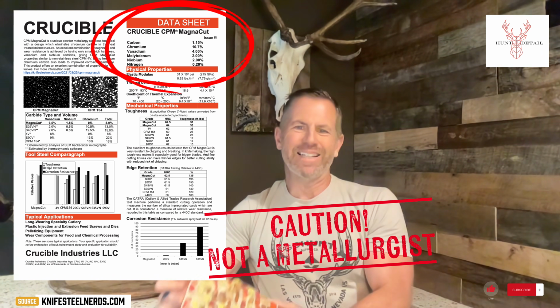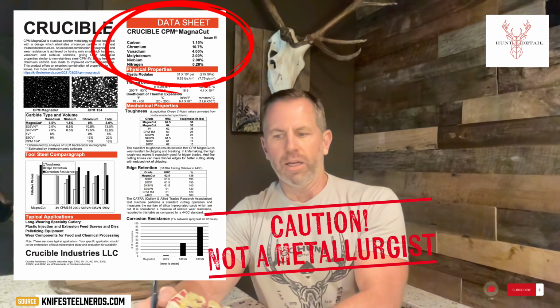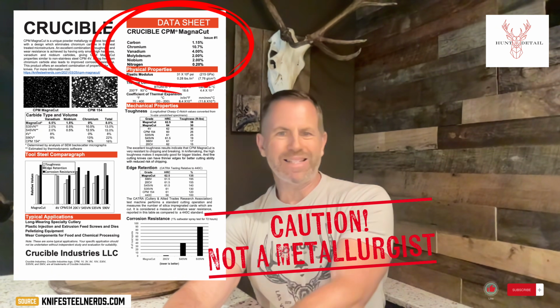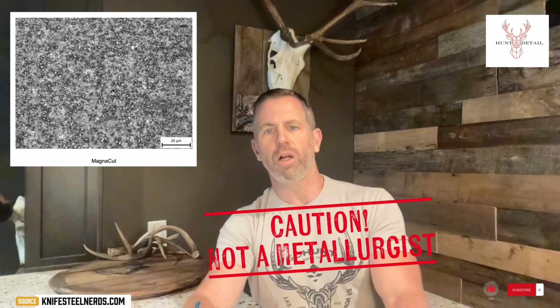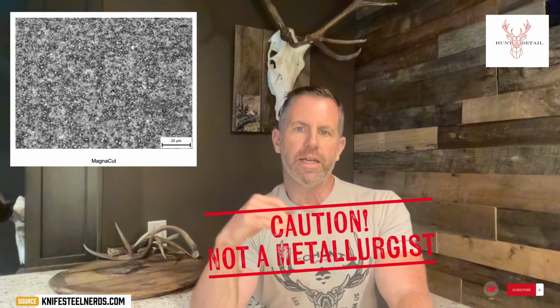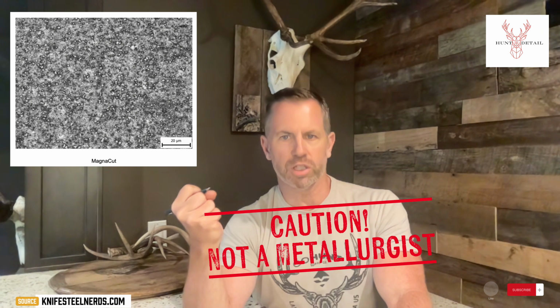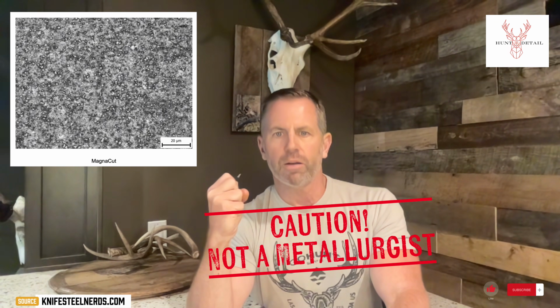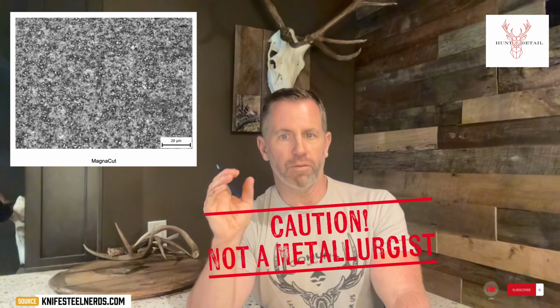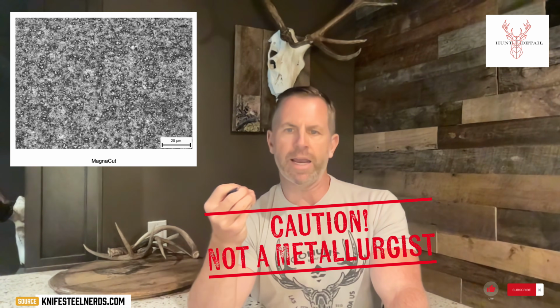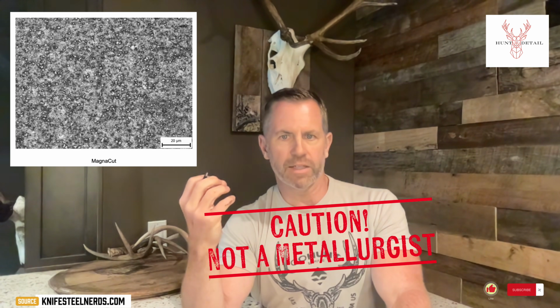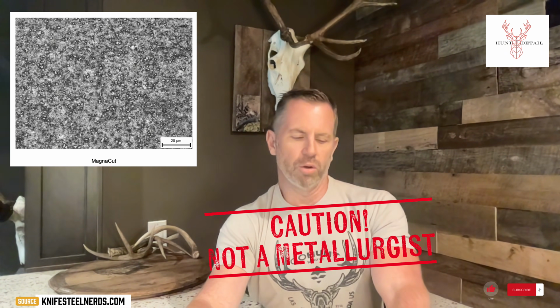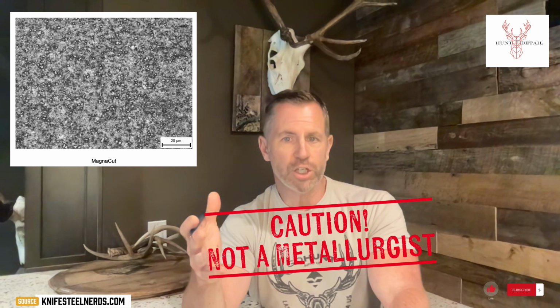And so by pulling it down to 10.7%, what it looks like he did was maintain the high level, almost the highest level of corrosion resistance, but also increase that toughness. So where you have the chromium, just the perfect amount of chromium to go into the knife matrix and create that film, that corrosive resistant film, but not create large brittle carbides that negatively impact toughness. And so this steel came out in about 2021-ish. And the number 1 knife is the Montana Knife Company Stoned Goat 2.0 MagnaCut.